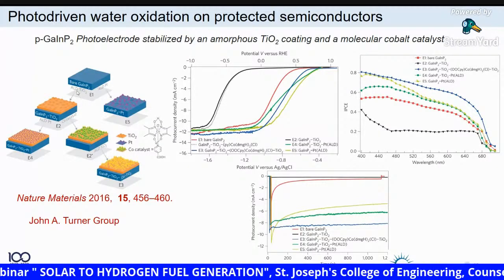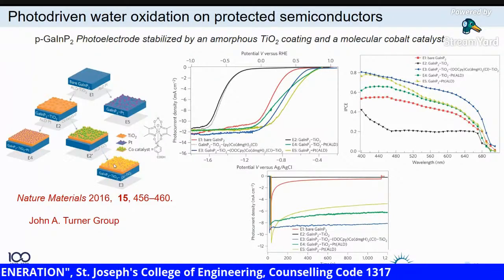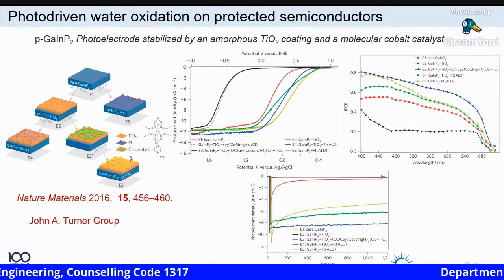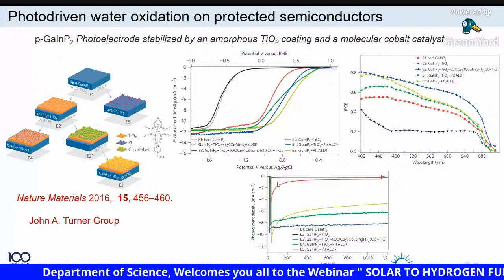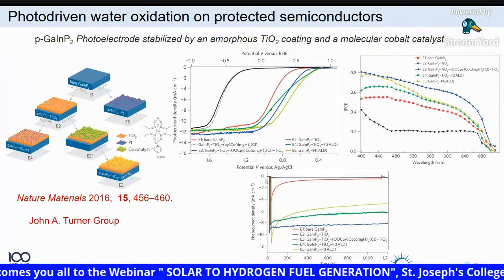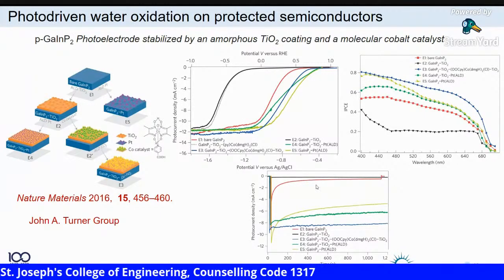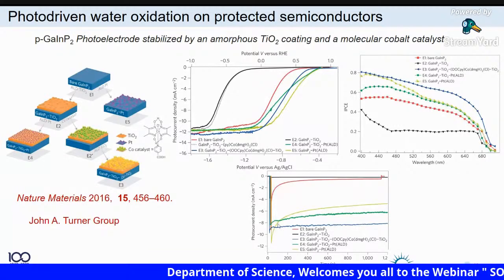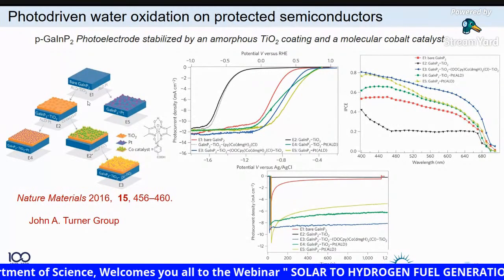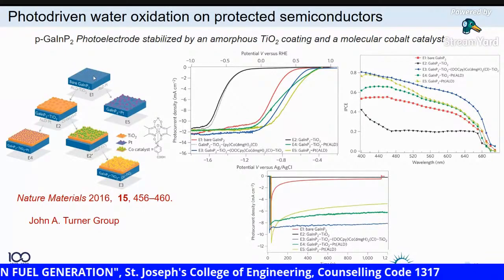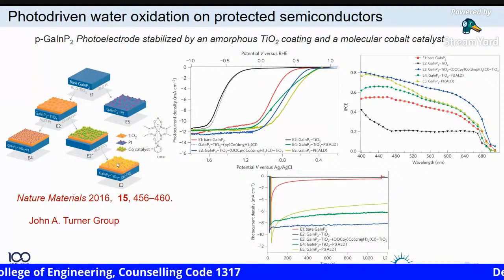Okay. So what will happen? So they coated again the co-catalyst material. You can see in the cartoon, okay, the yellow color or the green color. They coated a co-catalyst material, organic-based co-catalyst material, on the top of the layer. So see, this is the negative axis. Okay, don't confuse it. From start 0, the high number is here. So after coating the co-catalyst on the TiO2 layer, the green one drastically increased, and here is high photocurrent density but in a stable performance. So from these studies, what we understand is that even if you go for a protective layer coated on the primary water oxidation or water reduction catalyst, you must need another co-catalyst material in some cases. Okay, please keep in mind.